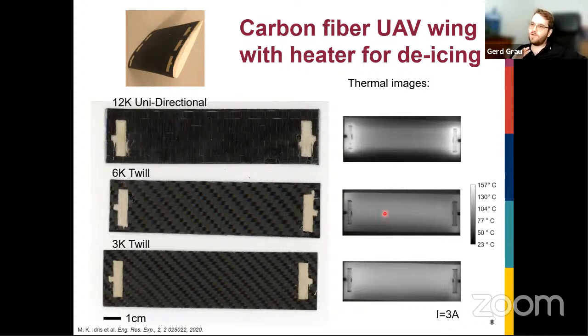But you have to be careful, for example, taking into account the structure of the carbon fiber. If you do this with these unidirectional carbon fibers here, where all the fibers run in one direction, they don't cross over each other, then the heat can't spread out, and you get this non-uniform heating. If you have a twill where fibers actually cross over each other, you get much more uniform heating here.